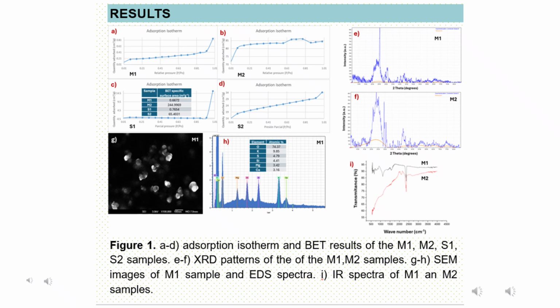The BET analysis shows a strong dependence on pyrolysis temperature. In this sense, the samples with low temperature, M1 and S1, both show a low surface area. This indicates an incomplete development of pores. On the other hand, the samples with higher temperatures, M2 and S2, show higher values. In this sense, the best was M2. This shows a high surface area.